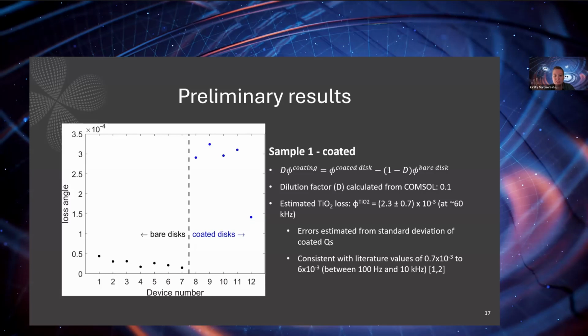And so for this particular case, we're going to do a ballpark estimate of the titanium dioxide loss using the average losses of the bare disks and the coated disks. And if we do that, we get 2.3 times 10 to the minus 3 with an error of 0.7 times 10 to the minus 3, which comes from the standard deviation of the coated quality factors. So this estimate of the error here is sort of a large overestimate of the error that comes from doing this averaging and from the scatter in the data.